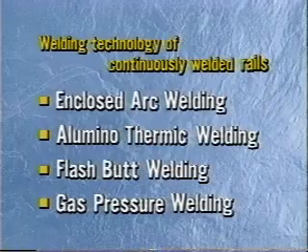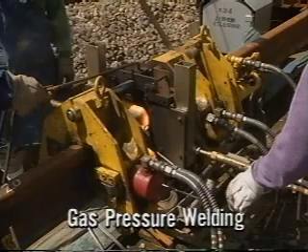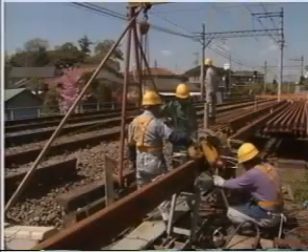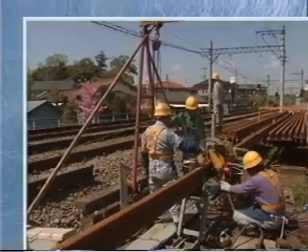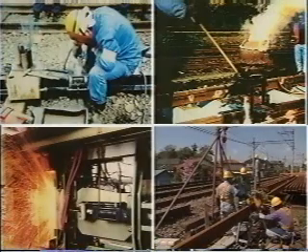In the technology of Hakusan's gas pressure welding, rails are welded by using oxy-acetylene flame and pressure is applied to the welded joint. Gas pressure welding is as capable as flash butt welding in strength and requires much less investment for its equipment than flash butt welding. Because of its outstanding mobility, gas pressure welding is the most suitable welding method for top welding as well as side welding.